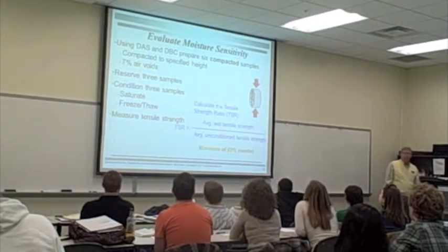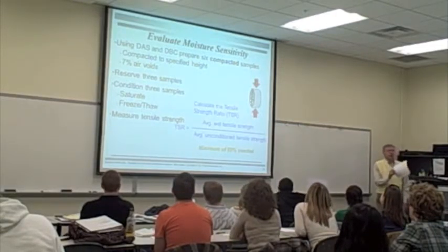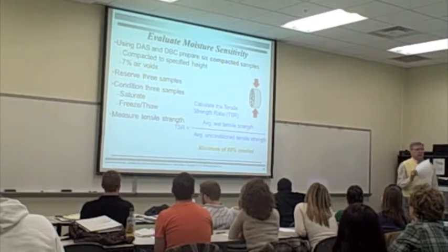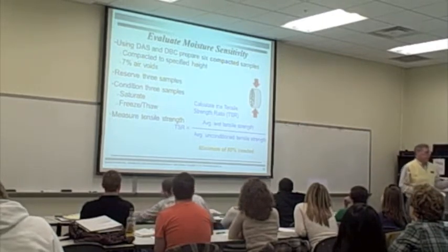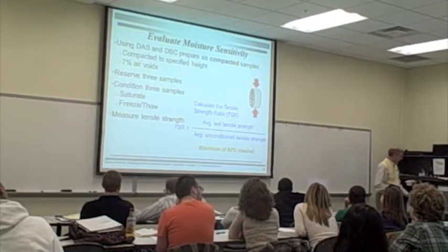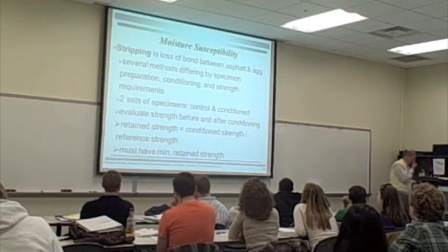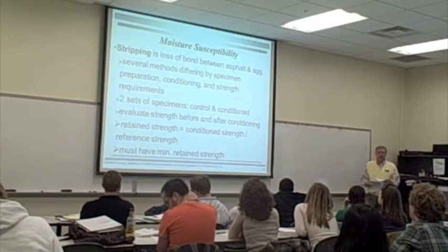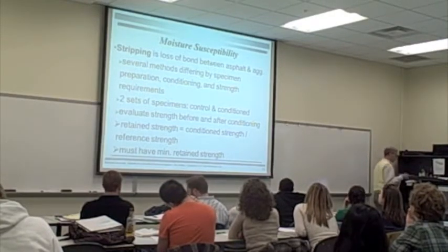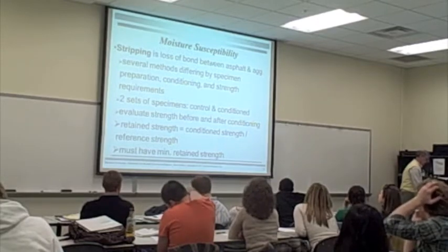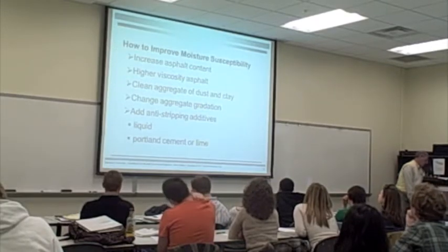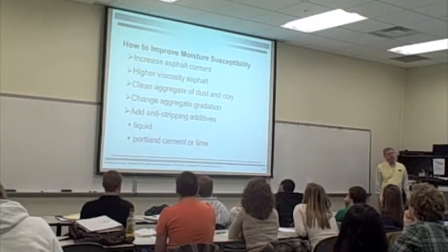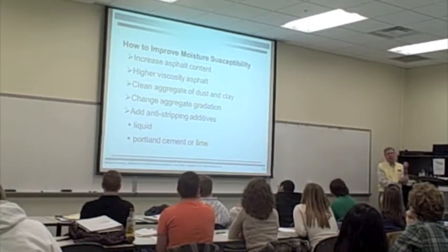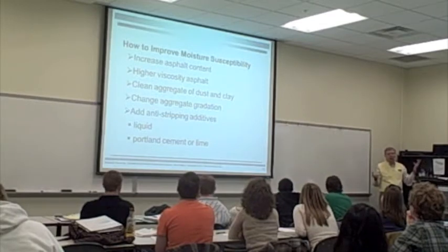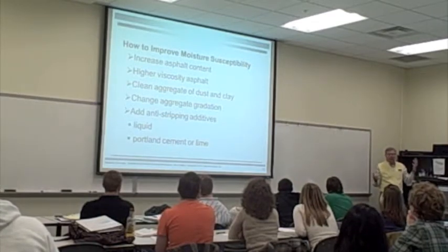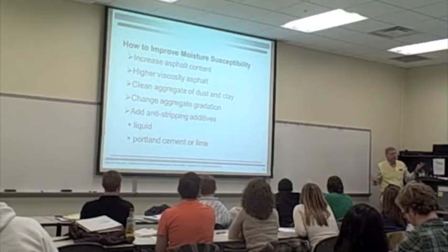Measure the tensile strength and compare the ratio. You want the strength of the conditioned samples divided by the strength of the unconditioned samples to be at least 80%. If you've done that, you've got a good product. If you failed that, then you can add anti-strip agents into the material, either liquids or powders, and improve the moisture susceptibility. It's kind of a big deal because if you get moisture susceptibility, you usually get it within a couple of years, and the asphalt just basically falls apart, right? If the aggregates aren't being held together by binder, they're just aggregates.